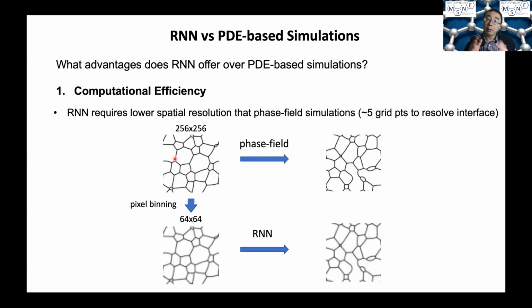For example, in phase field simulation of microstructure evolution, it's typical that you need to resolve the interface with a sufficient number of grid points. Right? Typically, you want to have 5 grid points to resolve the interface, right? And this limits the size of system you can simulate in a phase field simulation. This constraint is no longer obeyed by machine learning, right? So for machine learning, actually, what we can do is to coarse-grain the images, downsample the images, and then run the machine learning predictions on the coarser grid, and therefore be more efficient in spatial representation.